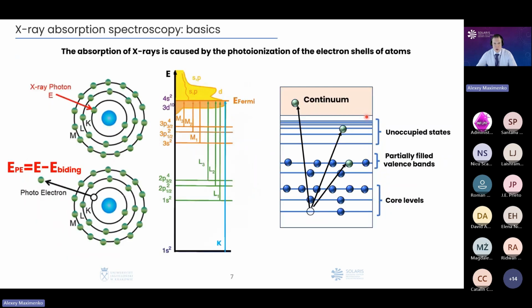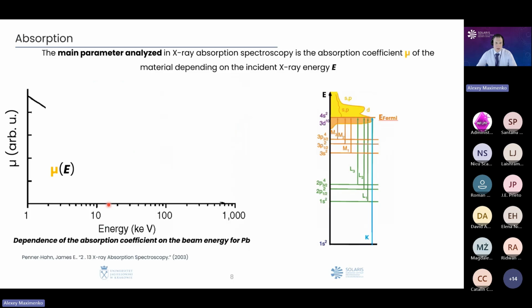When we speak about absorption of X-rays, we speak about photoionization of the electron from the core levels. The photoelectron which we excite from a core level, for example the K level, L level, or M level, is firstly excited to the unoccupied states, and then we could excite this photoelectron even to the continuum. The energy of this photoelectron in the continuum will be the difference between the energy of the radiation which we irradiate our atom with, and the binding energy between the electron on this core level and the nucleus.